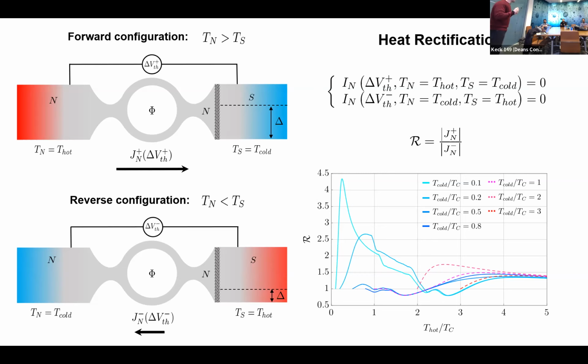Well, this can be explained by saying that delta V plus for the forward configuration is always different from delta V minus for the reverse configuration. You obtain this just by solving a couple of equations, basically imposing that the charge current is equal to 0 in the case of the forward and in the case of the reverse configuration. Simply because of the nonlinearity of the Fermi function, solving this numerically, you obtain that delta V plus is different from delta V minus, meaning that you're breaking left-right symmetry not at the level of the gap, but at the level of the thermoelectric potential, delta V plus and delta V minus. Indeed, you still see rectification even in the normal effective regime.